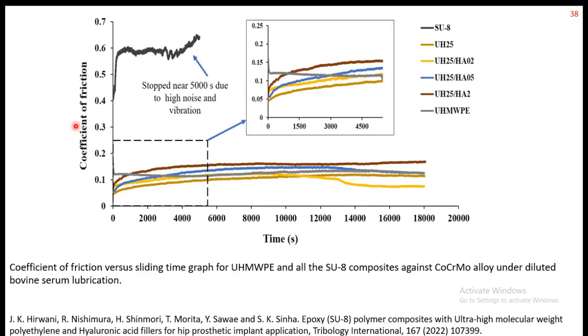Most importantly, we have to look at the coefficient of friction. It's actually quite low. For UH25, meaning 25% UHMWPE in SU8, pure SU8 gives a very high coefficient of friction, but as soon as you add 25% UHMWPE and some percentage of HA, hyaluronic acid, you get a very good surface with low coefficient of friction. HA02, meaning 0.02 weight percent, gives the most consistent low friction results.